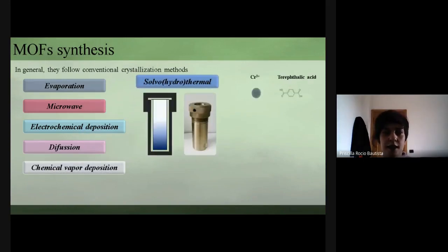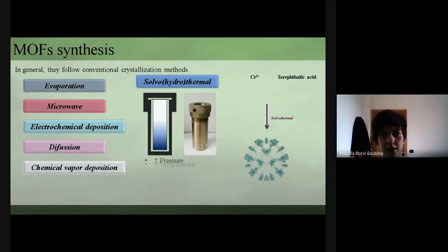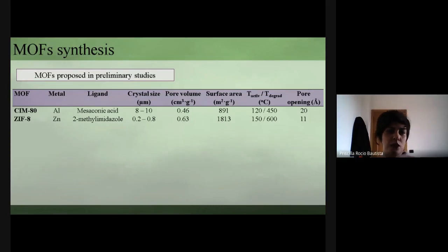During this process, the organic ligand and the metal salts are directly added in a reactor with a proper solvent. After being subjected to high pressure and temperature for a few hours, normally this type of reaction takes between 2 and 48 hours, a crystalline powder corresponding to a MOF is obtained. As a first approximation, two flexible MOFs are proposed, CIM-80 and ZIF-8. The term flexible implies some margin of movement in the material structure. In this sense, we have different shapes for the sorbent-analyte interaction.